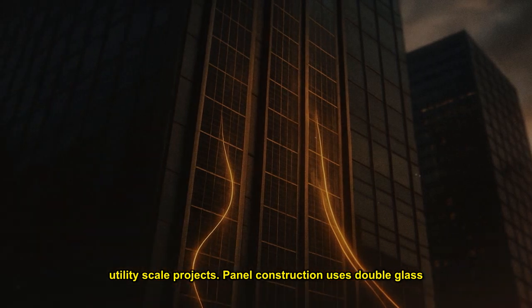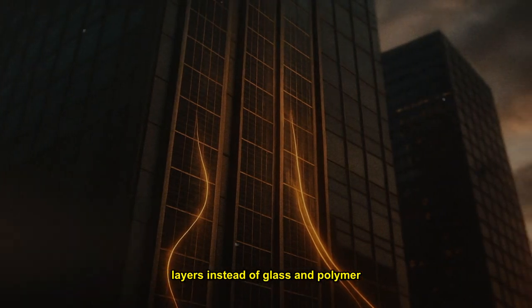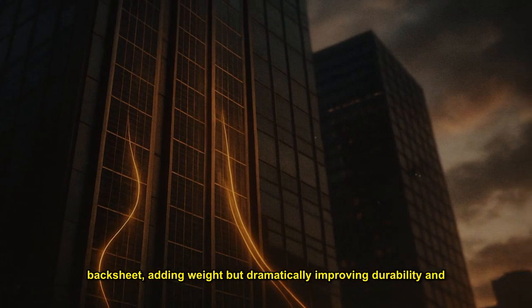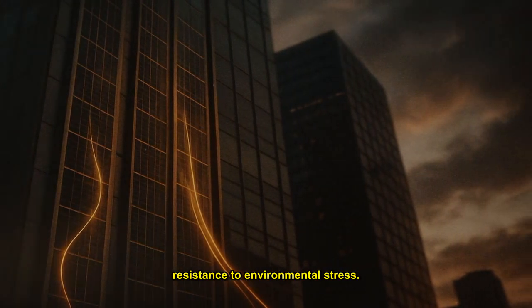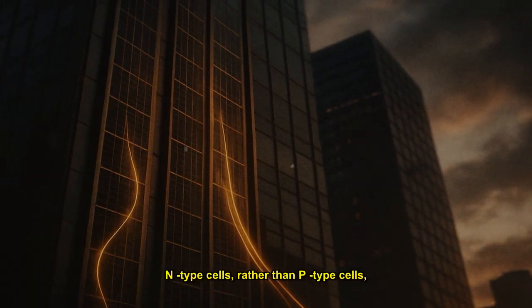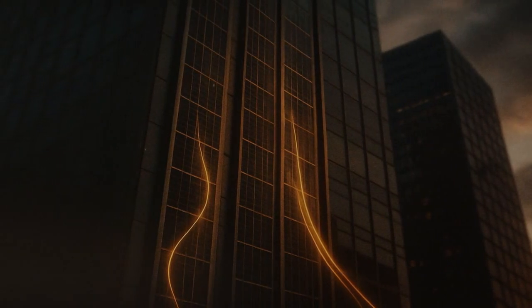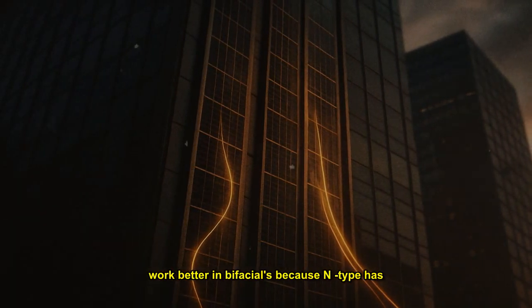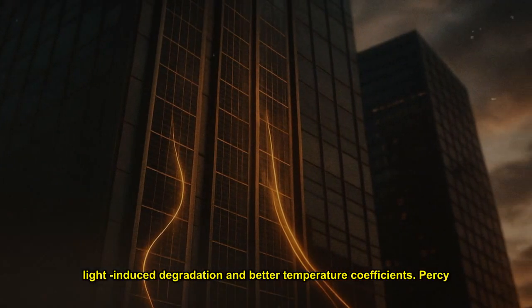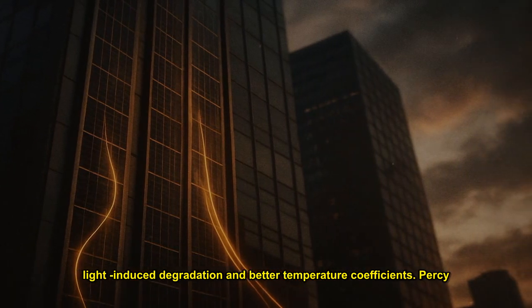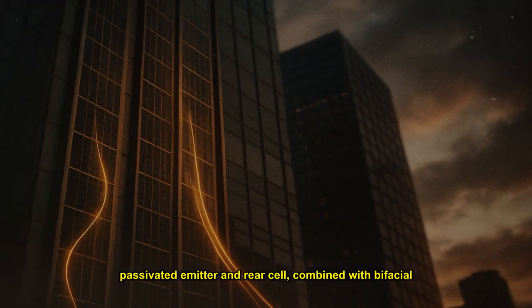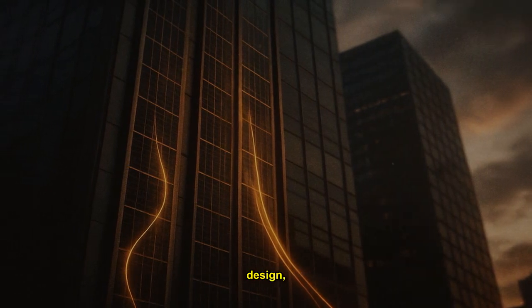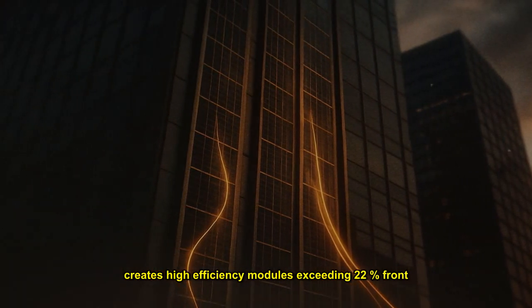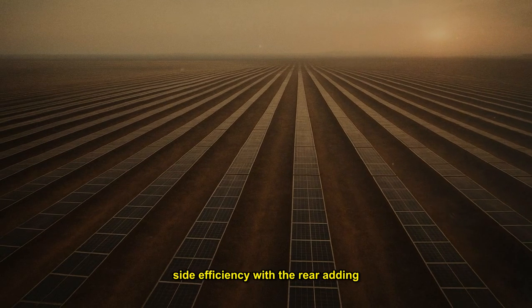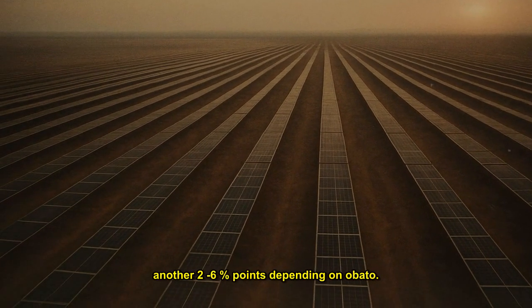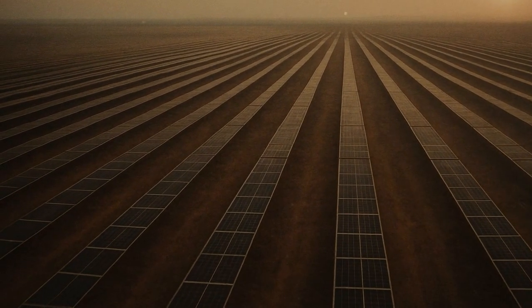Panel construction uses double glass layers instead of glass and polymer backsheet, adding weight but dramatically improving durability and resistance to environmental stress. N-type cells, rather than P-type cells, work better in bifacials because N-type has less light-induced degradation and better temperature coefficients. PERC technology, passivated emitter and rear cell, combined with bifacial design, creates high-efficiency modules exceeding 22% front side efficiency, with the rear adding another 2 to 6 percentage points depending on albedo.